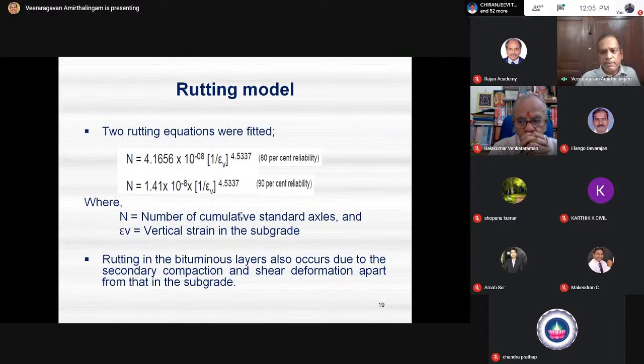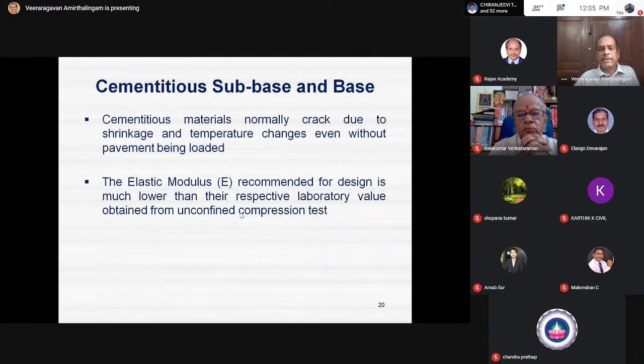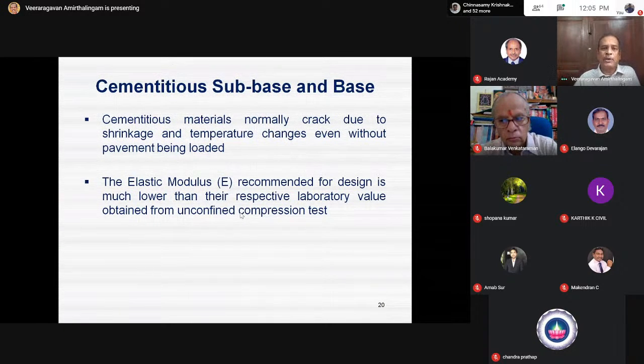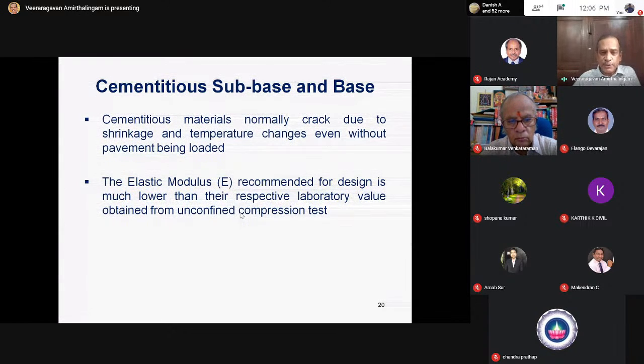So cracking, there are models, there are rutting models. We can go in for cementitious subbase and base courses. You should know that cementitious material normally cracks due to shrinkage, maybe due to temperature changes. So the elastic modulus for the design is much, much lower than the respective laboratory values. How much lower? I told 5,000 MPa. Today consider 1,000. Today consider 750 MPa, 500 MPa.